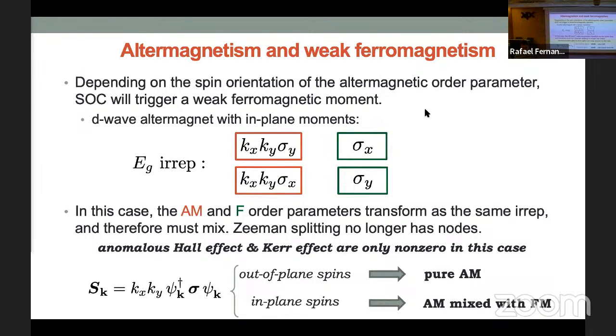Now, it depends on how you want to see that. What is interesting in this case is because I have ferromagnet, I'm going to be able to see manifestations of this, indirect manifestations of this altermagnetic order parameter in quantities that only exist if I have a magnetic moment, such as Hall effect, anomalous Hall and Kerr effect. So altermagnets, pure altermagnets do not have anomalous Hall or Kerr, but if the direction of the moments induce a mixture of ferromagnets, then they are realized. Okay?